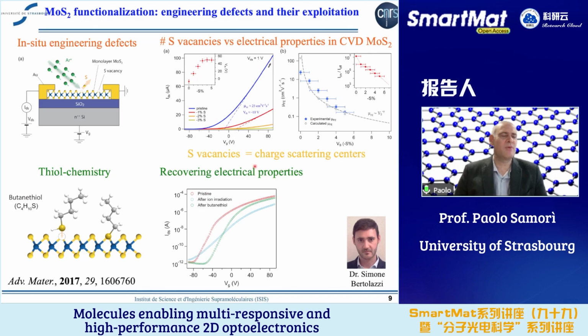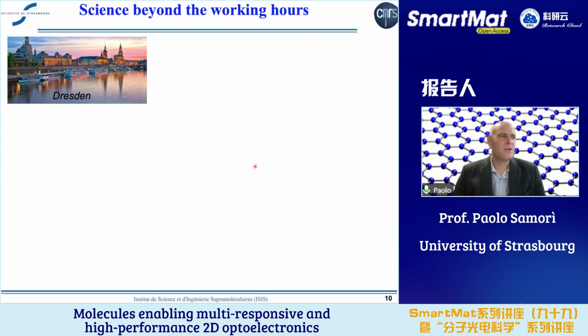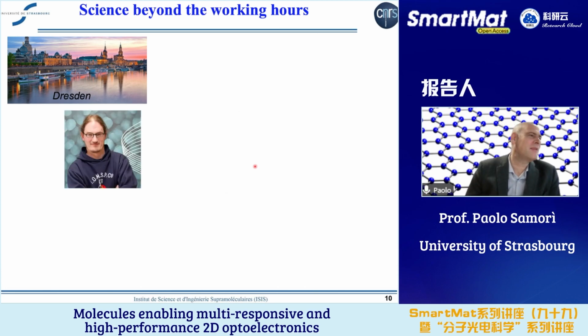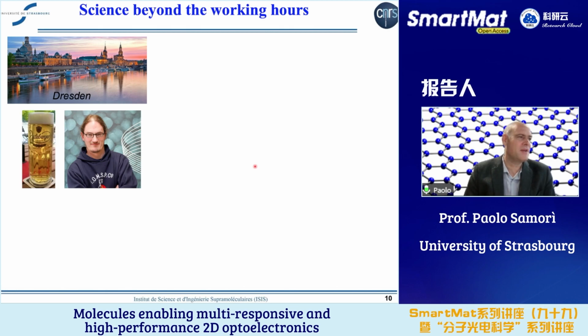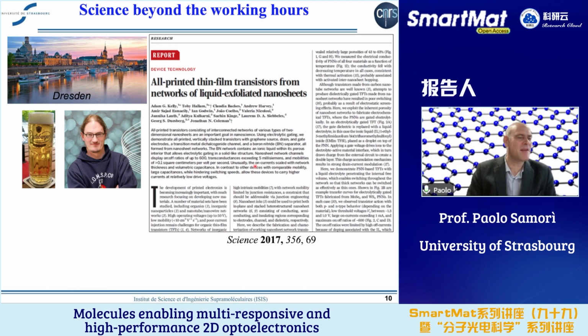Now, this is just a demonstration that thiol chemistry, which is well established for the interaction between thiols and gold, can be useful in order to control the functionalization of MoS2. And so then it happened that I went to a meeting in Dresden, invited by Xinliang Feng, and there I met Jonathan Coleman. Johnny Coleman from Dublin is a pioneer of liquid phase exfoliation of 2D materials. And actually, this was in front of a beer in the evening, and we were discussing the paper that he had just published in Science.